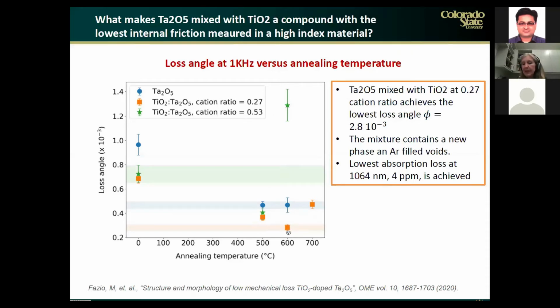And this at 600 degrees, again, is where we see this interesting morphology that contains nanocrystallites at voids. What is interesting also is that at this annealing temperature, we also measure the lowest absorption loss in the coating, which is 4 parts per million.